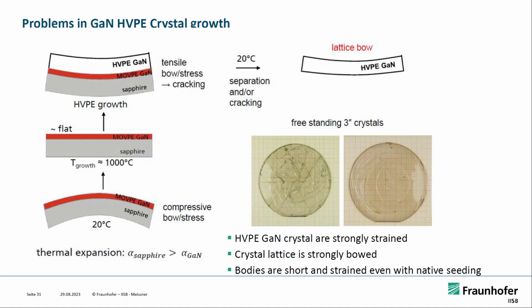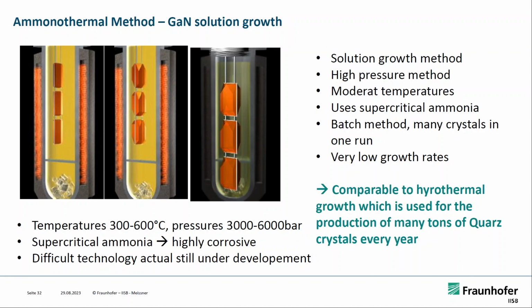So the whole crystal, even if it looks flat, is highly strained inside, because the lattice is strained. And if you're touching it, it may break; if you heat it, it may break; if you wait, it may break. So the strain has to go away, and what the strain is really doing to the lattice...